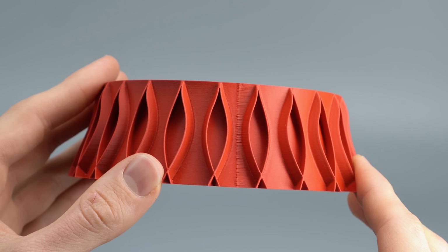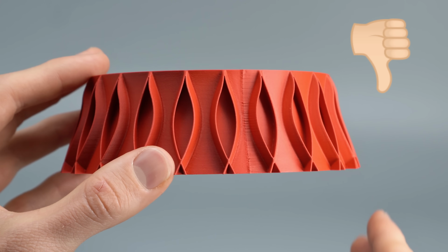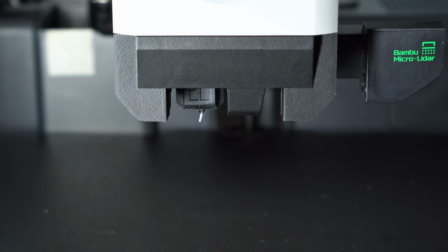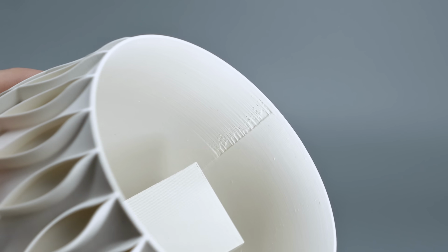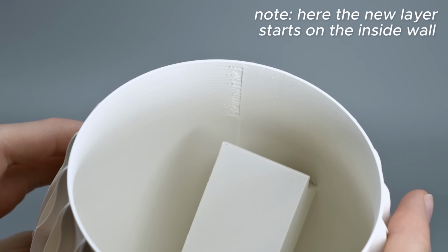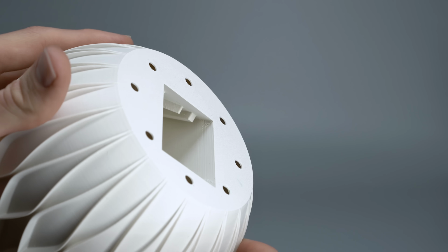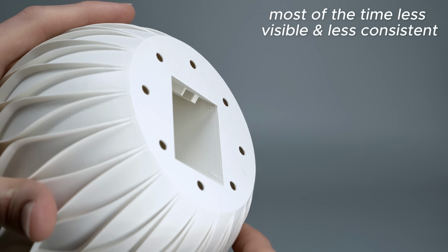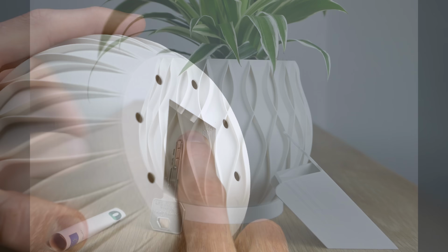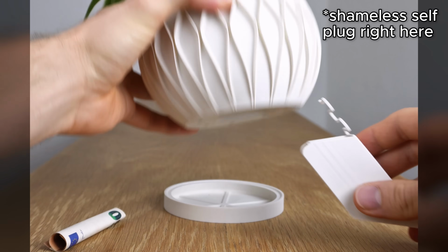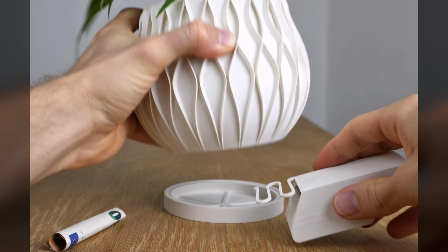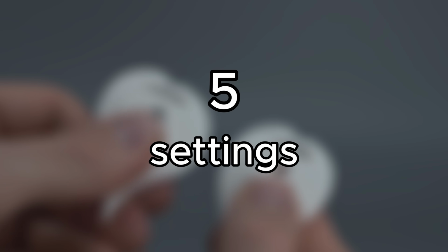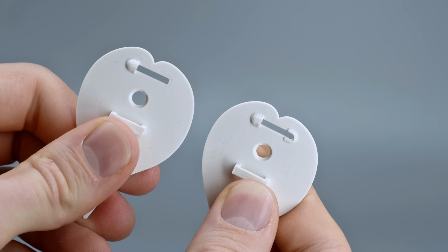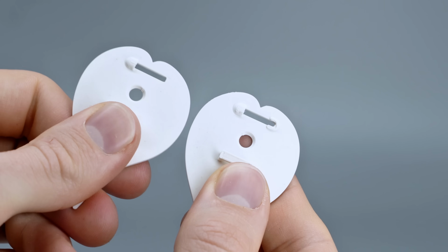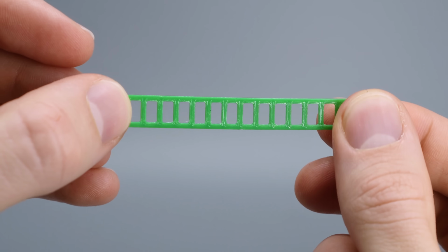But wait, this is just the tip of the iceberg. When moving the seam out of the corner, you can see how bad the print result actually is. It gets even worse with filament that oozes a lot, like this white PLA, or materials like PETG or TPU. Depending on the model, you can get this problem all over the print, like on the inside of the hidden box compartment, which is normally used for a pushlock mechanism to hide a small key inside. But definitely won't work like this. Let's take a look at different solutions and other misprints that indicate related low pressure problems, so you can get exceptional prints for any model in the future.